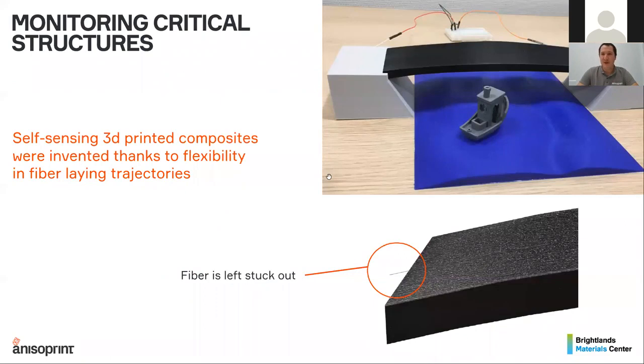And there are a few more examples of what you can do with fibrous materials, like self-sensing structures, where this is actually a use case that was made by one of our customers, one of our partners, Brightlands Material Center. So by incorporating the conductive carbon fiber inside the plastic structure, and by attaching it to the current source, you can measure the resistivity, and you can measure the deformations in the structure like a sensor.